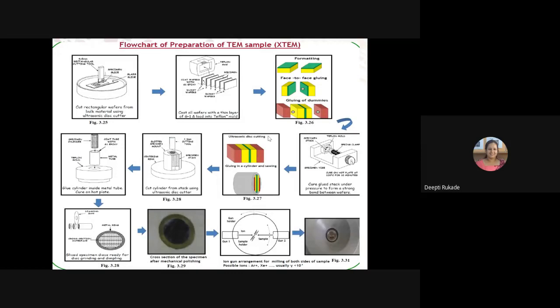Here it requires a lot of patience, and you have to grind it till the thickness goes down to some 100 microns. You measure the thickness, you grind it again. You measure the thickness, you polish it again. So you have to redo this process a lot of times. Once that is done, you use a dimpler and that 100 microns, you further reduce to some 50, 60 microns. So the film has now become very, very thin and very, very fragile.